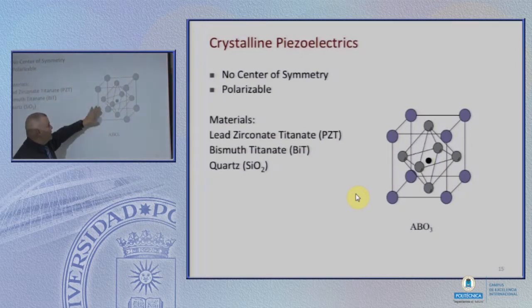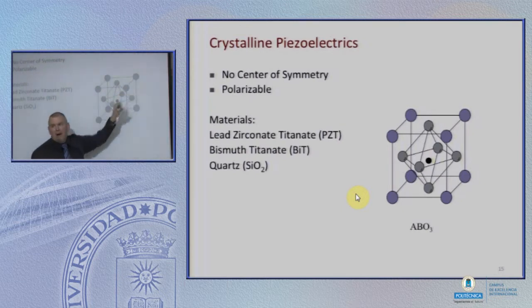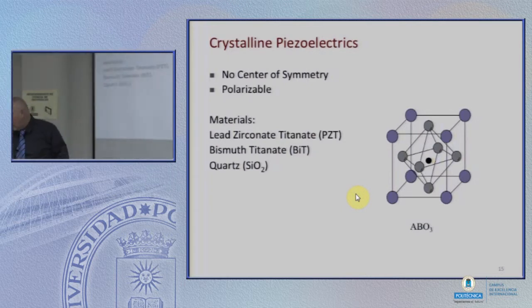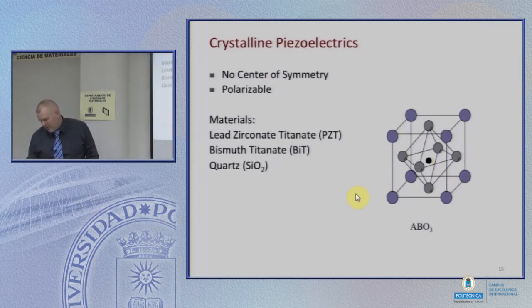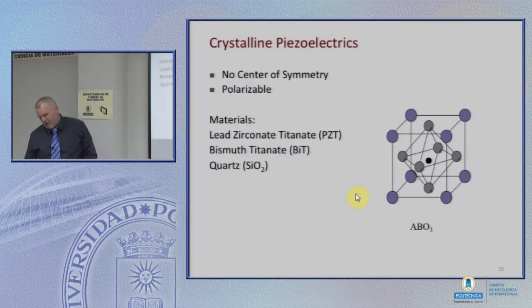It's also possible for these materials to be, and I'll show examples of these materials, where they're rhombohedral, which means they have a polarization along the body diagonal. And so that ion will shift this way or this way. Of course, picking which orientation that extension is for it to actually be rhombohedral, there are four possibilities. The four possibilities for rhombohedral, the three possibilities for tetragonal, all come into play in terms of what we show and how the measurements occur. And it's all actually, I think, a very beautiful part of crystallography.